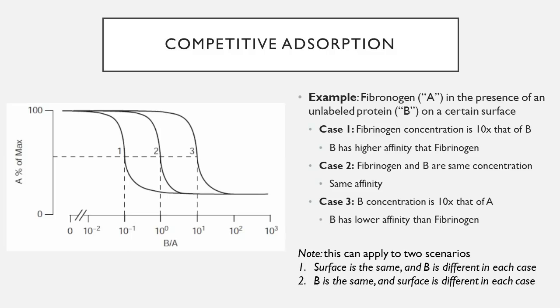Now, just like with the adsorption and depletion studies, there's cases where we want to look at adhesion of just single proteins, like the example I just went over. And there's also competitive assays where we want to compare the relative adsorption of different proteins in combination with each other. Now, in a typical competition assay, you would combine two different proteins at different concentrations, which here, like in the example, is given as a ratio of an unlabeled protein to the labeled protein. And the labeling is just one way of actually seeing the presence of that particular protein. You could have a fluorescent label, a radioisotope label, just some way to actually measure that protein of choice. And then you measure the amount of that adsorbed protein on the surface as a percent of the maximum binding that it can possibly do.